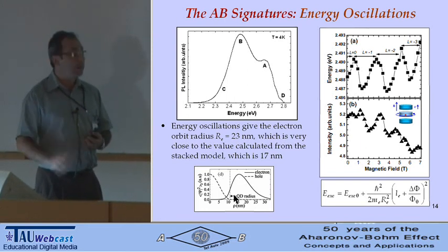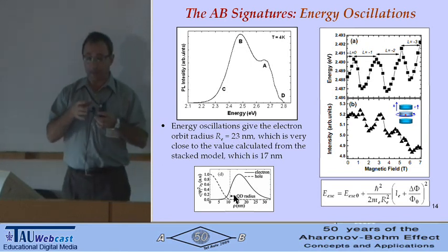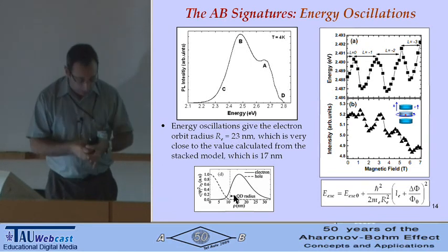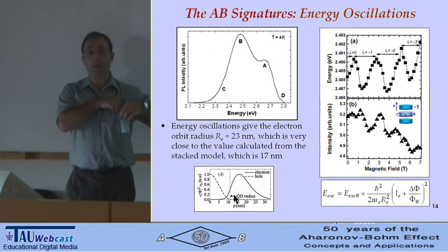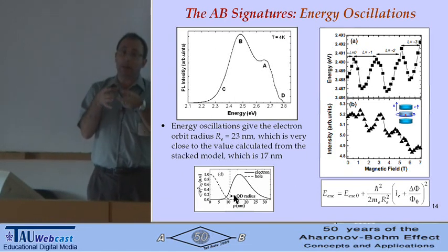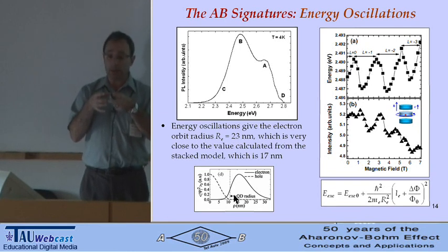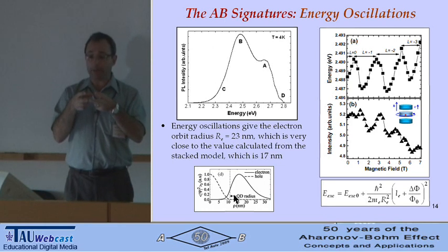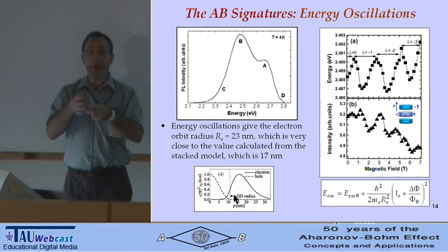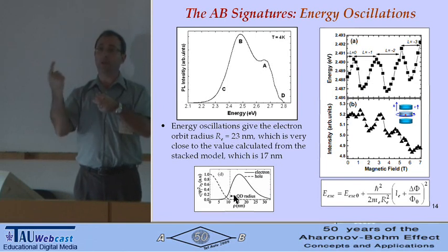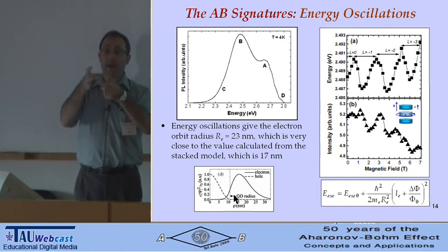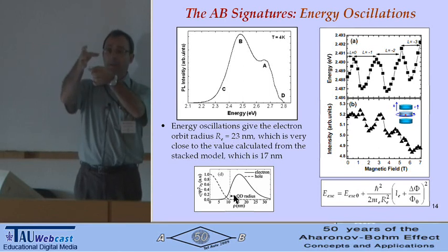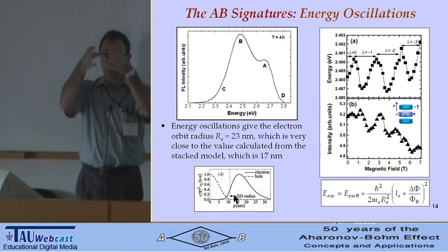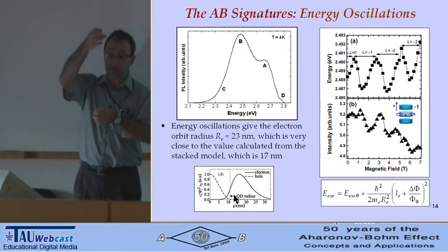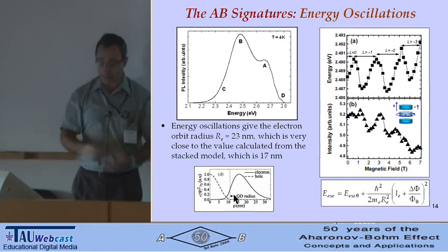So why is this such a strong effect here? I have to go back a little to the stacked model. If you have self-assembled quantum dots, the problem is that they're all different sizes. So if you look at a single dot emission, you don't expect to see very strong oscillations, because each quantum dot will have oscillation at a different magnetic field due to its different radius. However, with a stacked model, the electron moves along the whole column, and basically averages out not only the size of the quantum dot, but also the mis-stacking of the quantum dots. Because if I have quantum dots like this, the electron will move in the whole orbit, and that's why the effect is so strong. So having a stacked columnar structure is very important for observation of this type of effect.